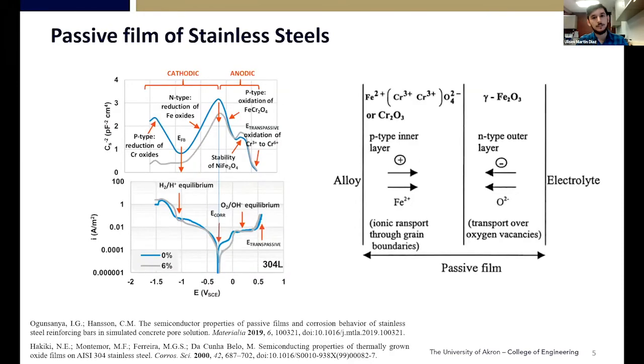However, this passive film is not only formed by the chromium oxide and the spinel phase, it also depends on the potential that we are at, as we can see from the Mott-Schottky plot combined with the CPP, where we have this relation that depending on the potential, for more cathodic potential, we'll have the reduction of chromium oxide, we'll have the p-type semiconductor.